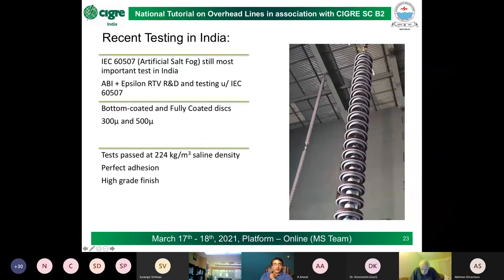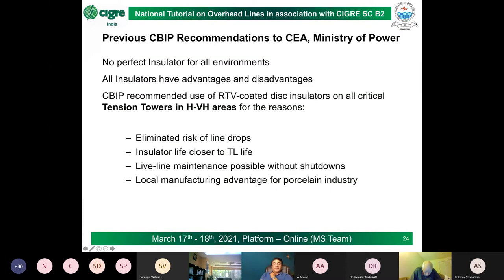Everything worked very well with the salt fog. Adhesion was perfect in the end. The finish was perfect. All in all, we managed to do this with the coating applied in such a way that it did not need to modify the packaging of the insulator after it is done, which is a remarkable thing, considering packaging is a major issue for coated insulators.